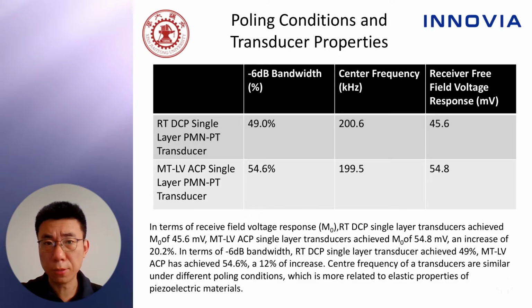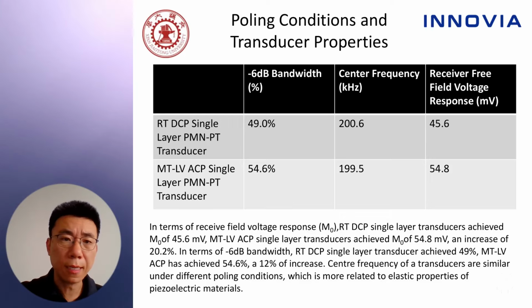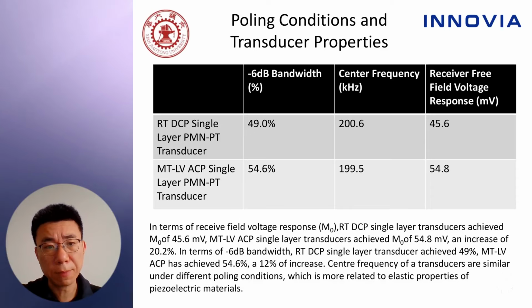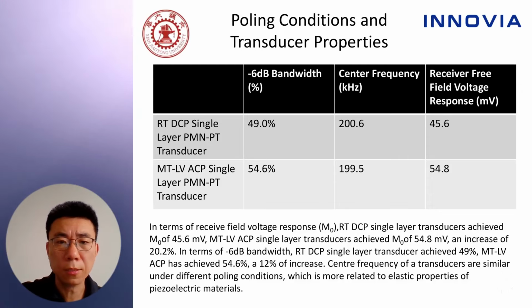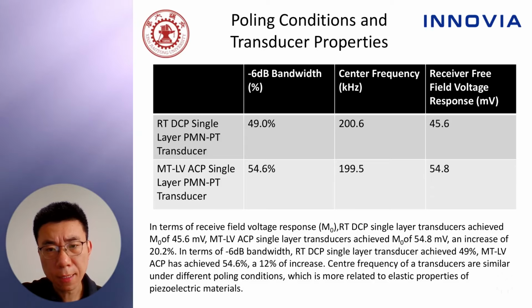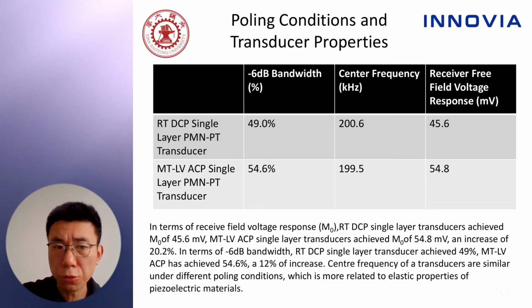If we are looking at the transducer properties, which corresponds to the conventional poling method, which is RT-DCP, and that of the best poling method that we obtain from the material properties, which is MT-LV-ACP, we learn that in terms of received field voltage response, M0, the RT-DCP single layer transducer achieved M0 of 45.6 millivolts. The MT-LV-ACP transducer achieved M0 of 54.8 millivolts, an increase of 20%. In terms of minus 6 dB bandwidth, the former gives 49%, whereas the latter gives 54.6%, a 12% increase. If we consider the center frequencies between the two transducers, they're pretty much similar.